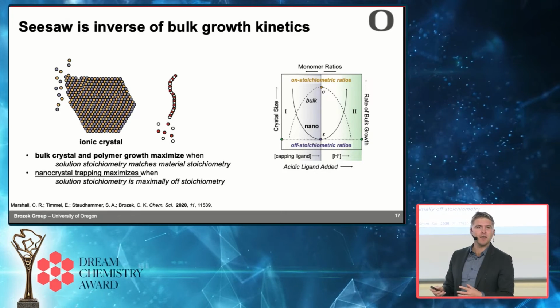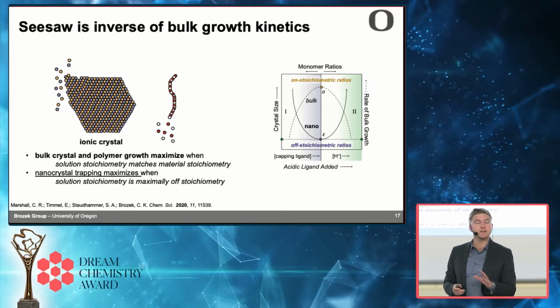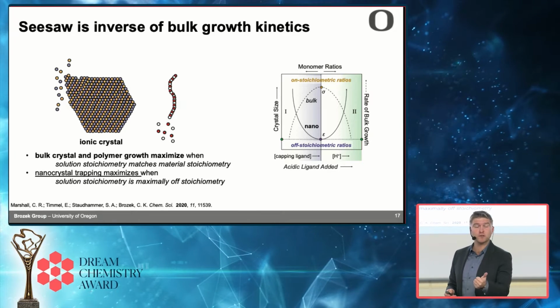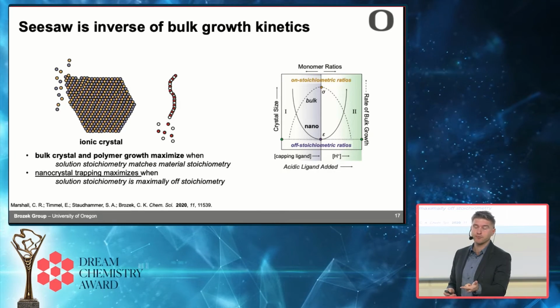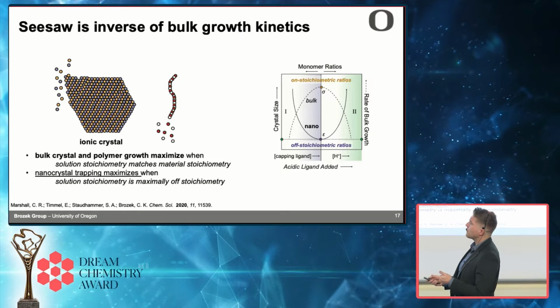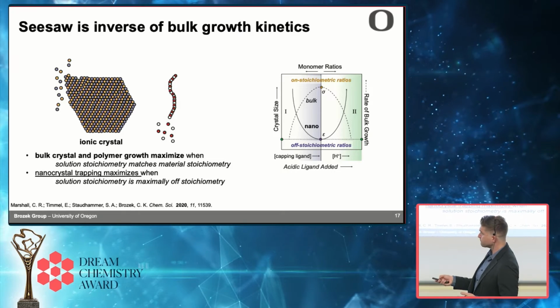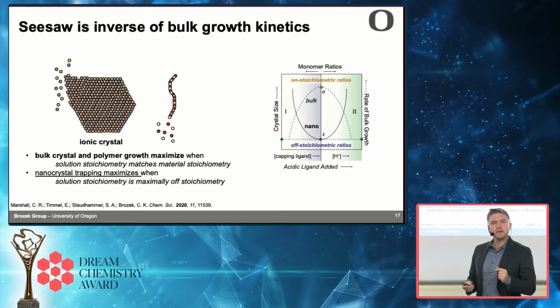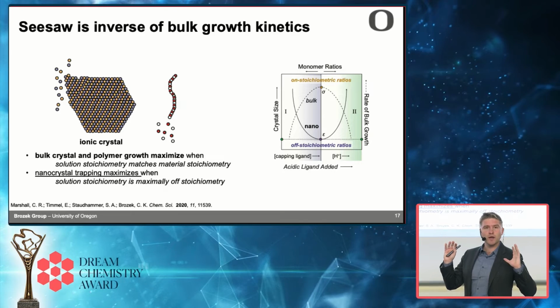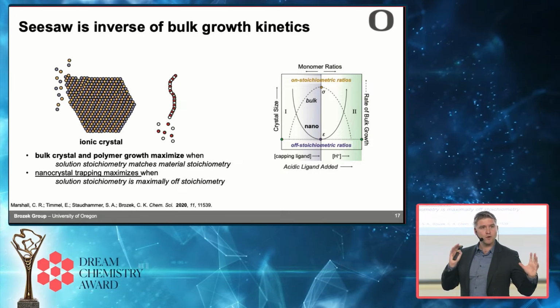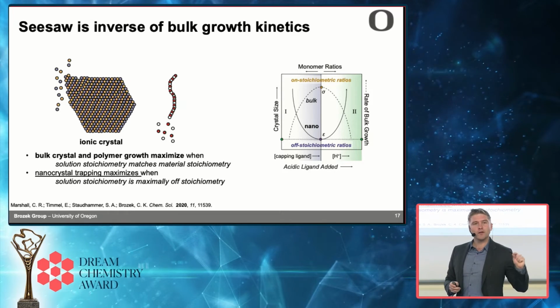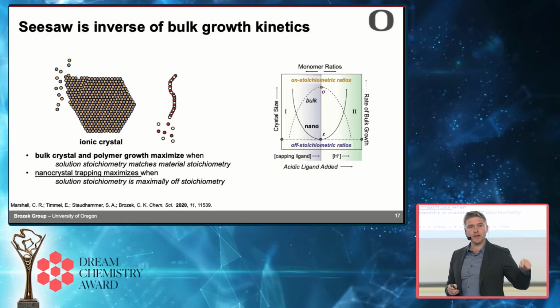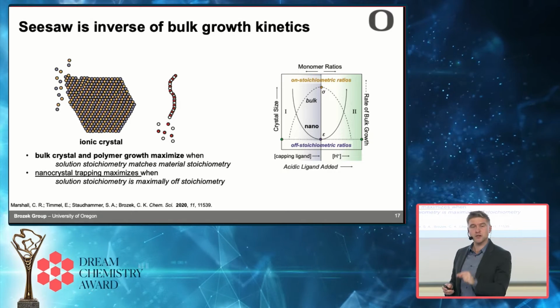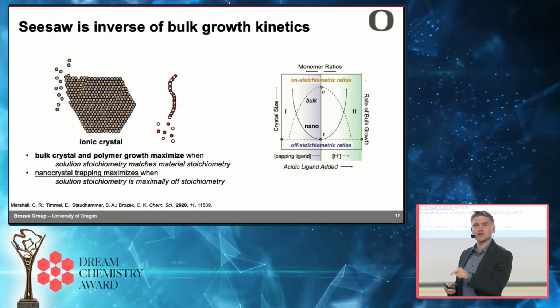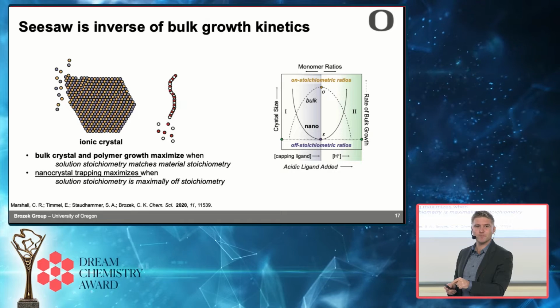This understanding that we came up with is totally consistent with how people have thought about how crystals grow in general and how polymers grow. So when people talk about the growth of ionic crystals and the growth of polymers, they say that you're going to get the biggest molecular weight species, whether it's a polymer or an ionic crystal, when the stoichiometry of the reaction media looks as much as possible like the stoichiometry of the thing that you're trying to make, okay?